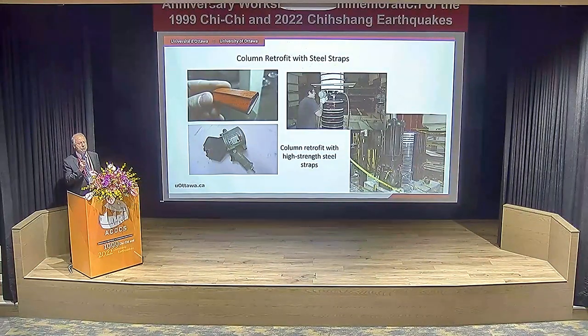Extending this concept to building columns created challenges because it's difficult to wrap 7-wire strand around smaller cross-section building columns. So instead we tried using packaging strips, which are high-strength steel strips used in the packaging industry. They have 800 MPa strength, and they usually use a handheld device to crimp the strips. We wrapped the columns similar to using 7-wire strands, except this is much easier, obviously, to bend in this case.